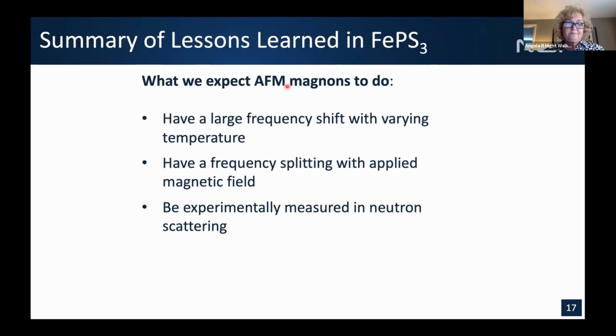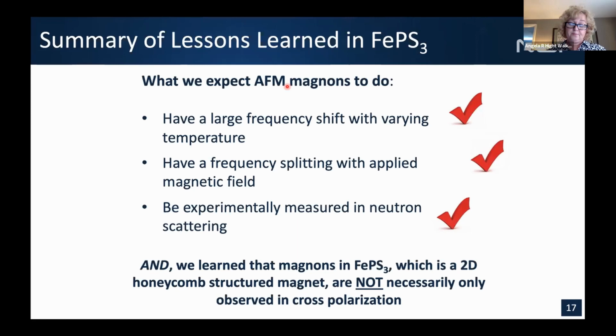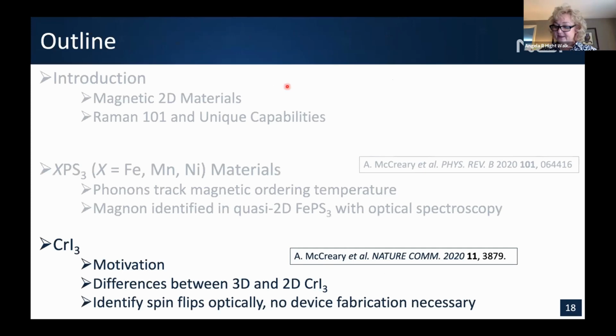So let's summarize the iron PS3. If it's an antiferromagnetic magnon, we will see frequency shift with temperature. We would expect the frequency to split with applied magnetic field, and we expected neutron scattering. And sure enough, all three things occurred. And furthermore, we learned that perhaps the way we think about the magnon polarization needs to be expanded a bit when it comes to the 2D limit. All right, let's move on to the chromium triiodide.